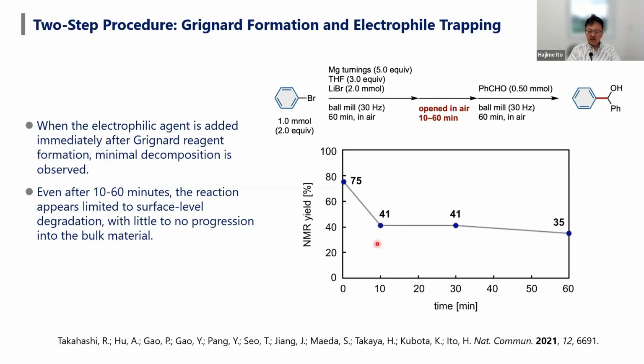This result clearly shows that the Grignard reagent prepared by ball milling reaction conditions is relatively more stable compared to the reagent prepared in solution phase reaction conditions.